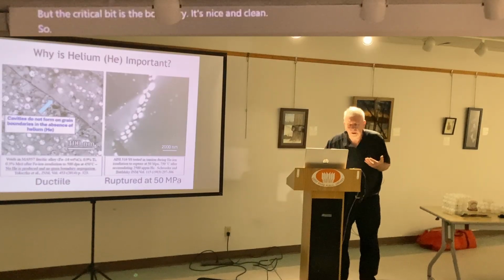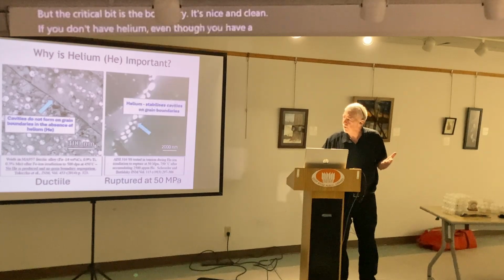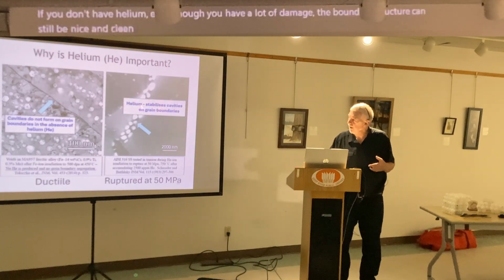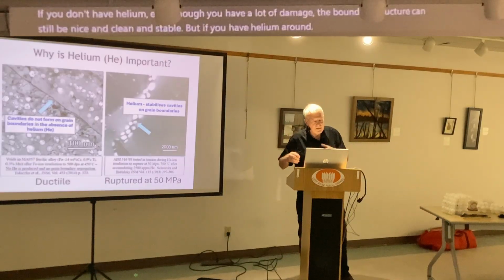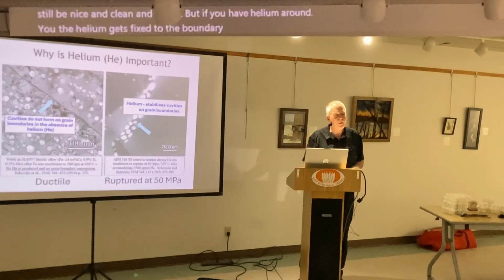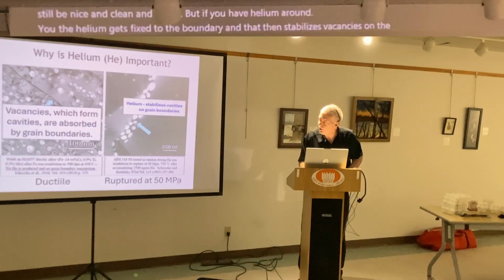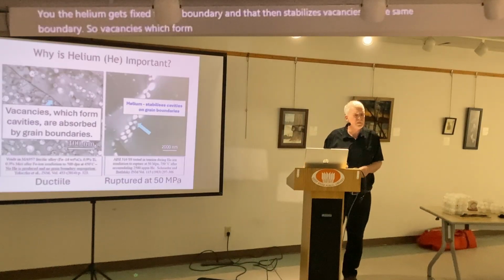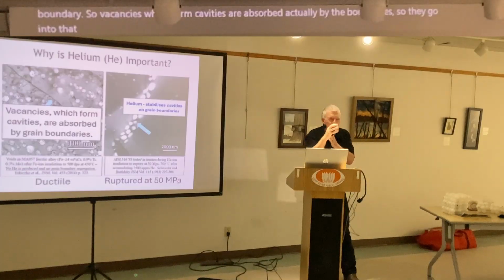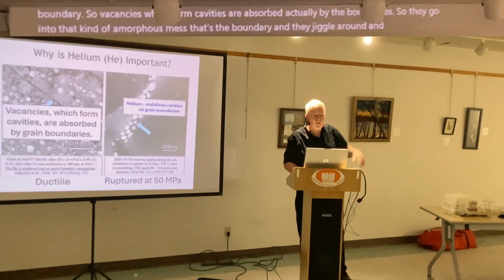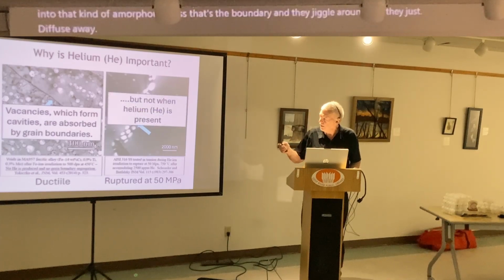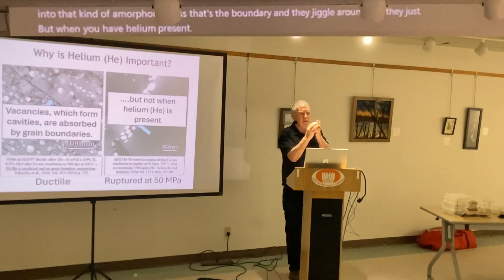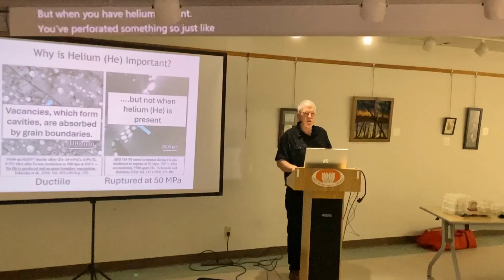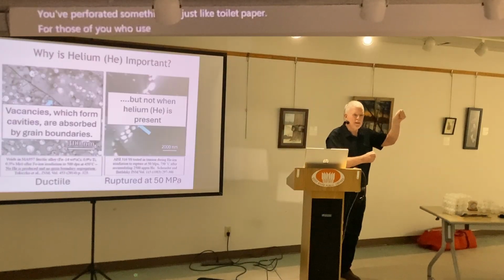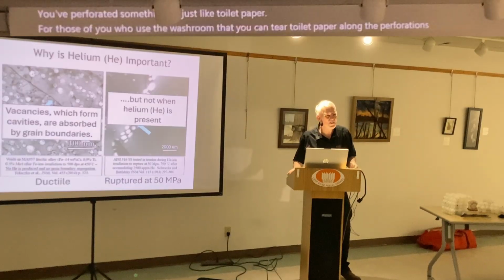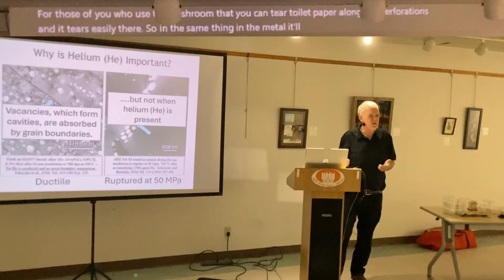So if you don't have helium, even though you have a lot of damage, the boundary structure can still be nice and clean and stable. But if you have helium around, the helium sticks to the boundary, and that then stabilizes vacancies on the same boundary. Vacancies which form cavities are otherwise absorbed by the boundaries. They go into that kind of amorphous mess that's the boundary, and they jiggle around and just diffuse away. But when you have helium present, you've perforated something. Just like toilet paper, you can tear it along the perforations, and it tears easily there. The same thing in a metal: it'll tear easily where you have perforations along the boundary.